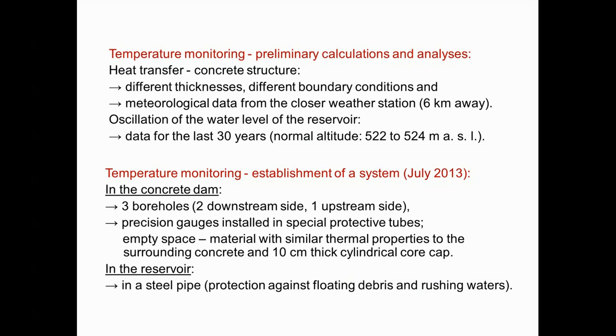Before establishing the temperature monitoring system, preliminary calculations and analysis of heat transfer in the concrete structure were performed. Different thicknesses, different boundary conditions and meteorological data from the nearest weather station were taken into account. The oscillation of the water level of the reservoir for the last 30 years was also analyzed. Based on these results, the temperature monitoring system was established. Three boreholes were made in the concrete dam — two on the downstream and one on the upstream side — with concrete temperature gauges installed in special protective tubes.